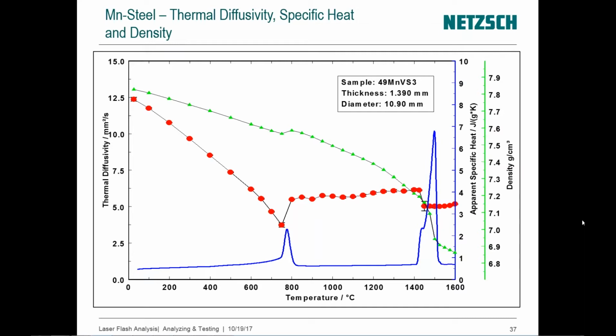First of all, if the specimen is not changing, if the specimen is stable at that temperature, the 3 values obtained for diffusivity should be fairly similar. If there is no change in the sample, it's not expected for the diffusivity to change. It is sometimes a way to statistically get good values or reproducible values. Number 1. Number 2, if those diffusivities change because the sample is shrinking or because the sample is unstable or something,